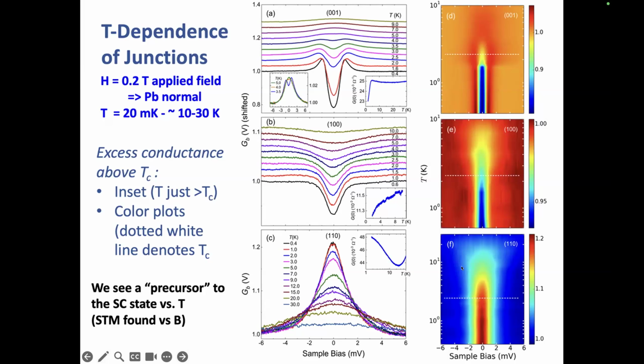If you remember a conventional superconductor like lead or niobium-3 tin, above TC you're a weakly correlated Fermi liquid, and below TC you've got a gap. Here, we know we're unconventional because we pick up non-Fermi liquid behavior in our planar tunneling that happens above the gap. You see it sometimes a little higher, sometimes a little lower. You can explain all that with Fano effects between the f level and the conduction electron. But in any case, we see a precursor.